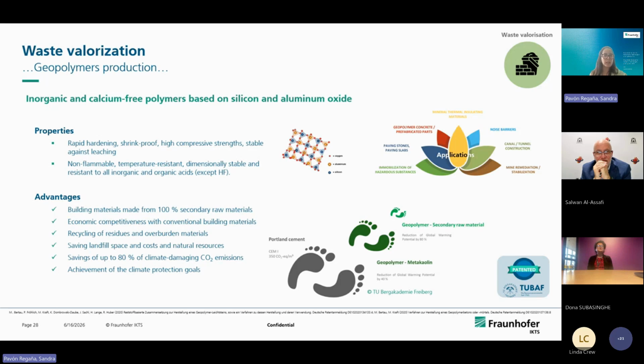It is inorganic and calcium-free, polymers based on silicon and aluminum oxide. So the properties are really similar to the cement industry, but a little bit better, because the advantage that this material has is that it is 100% built of secondary raw materials. And that means that we are saving up to 80% of climate-damaging CO2 emissions.